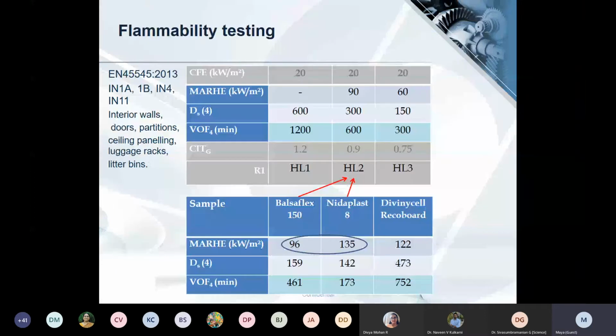So this is the testing of the panels, and this was done according to EN45545:2013, which is the European standard for fire safety in railway carriages. And here, the MARHE, which is the maximum average rate of heat release, was found to be lowest for the sandwich panel containing the balsa core. And this was falling into the category of HL1 and HL2, which shows the hazard levels.